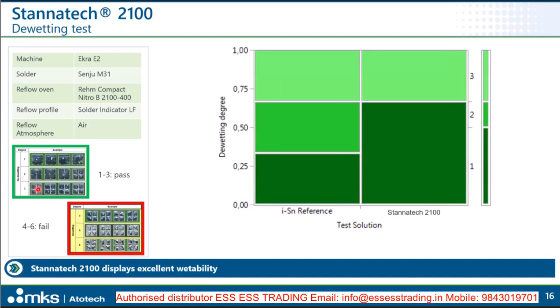In grade 3, the solder gets liquid and stays where it is, does not connect, but it does not de-wet. And so all indications for de-wetting start from grade 4 upwards. There we really see areas where the solder removes from the pad edges, and this is what we definitely do not want to see. So that would all be a fail.